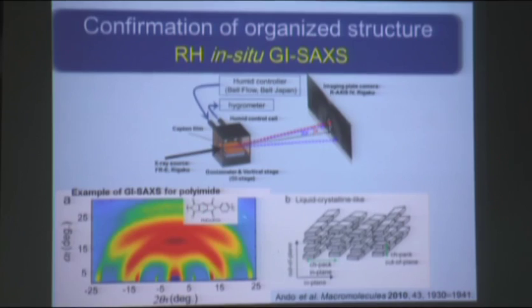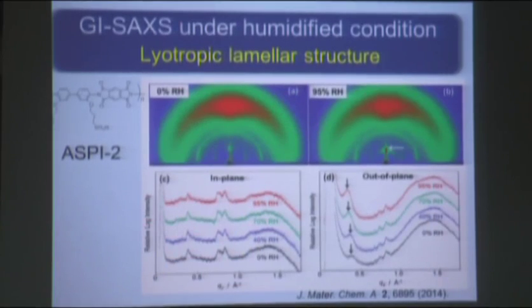This is not ours, without the sulfonic acid group, yes. So the X-ray comes here. This is simple. The scattering gives two-dimensional imaging. So we can see this is the out of plane direction. This is the in plane direction. So Professor Ando suggested from this data that this polyimide might have organized structures, using the liquid crystalline properties. This is the actual data of ours with the sulfonic acid group. So you can see the two-dimensional pattern in the dry condition and humidified condition. This is in plane. In plane means here, cross-sectional. Then out of plane is this direction.